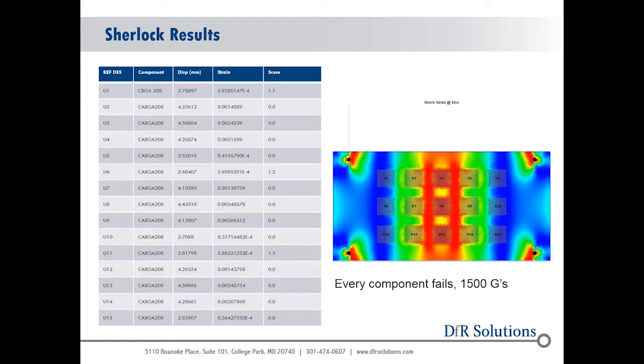and a strain-based criteria. And this is another thing that you can think about when you're laying out a circuit board: am I forming what we call sort of alleys or actually hinges on my circuit board? You can see I've got a large concentration of strain or bending because of the way this board has been laid out. And actually these 9 components in the center have very similar strain levels, so they're all going to have very similar time to failure, drops to failure, because they're being subjected to about the same types of board level strains. And then, where Steinberg wouldn't predict parts at lower doses failing, a strain-based criteria would.